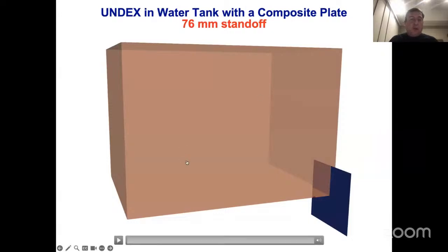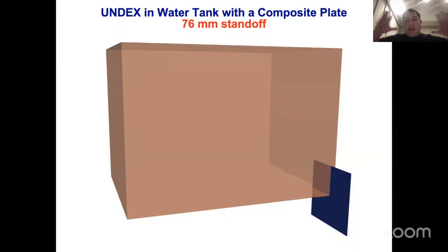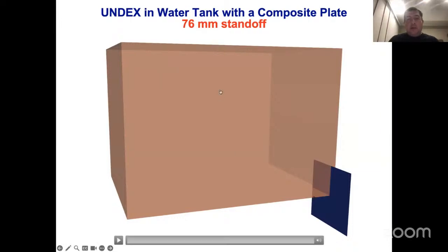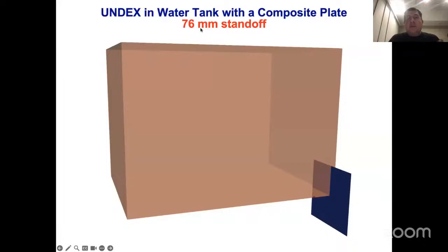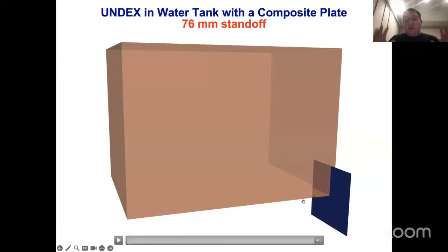And so here's a calculation of a composite plate. This is a quarter of the volumetric domain that's filled with water. There is a charge here. These are not full scale, these are lab scale experiments. So the standoff is 76 millimeters, which is even less than 10 centimeters. So these are fairly small structures.